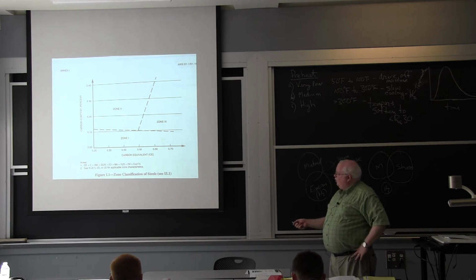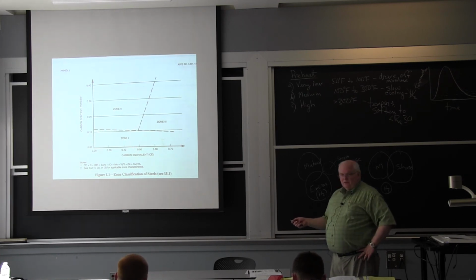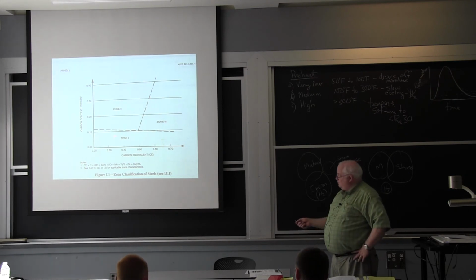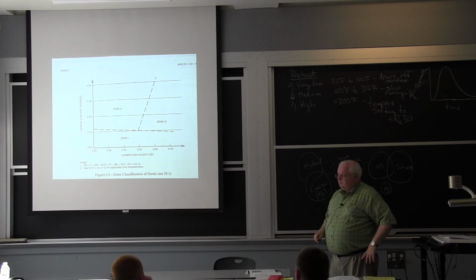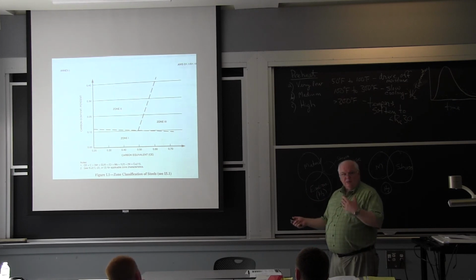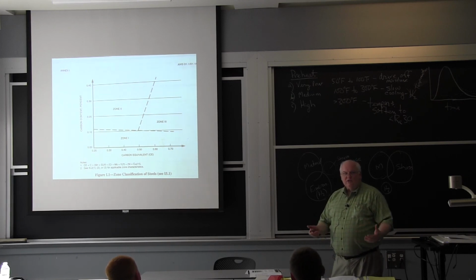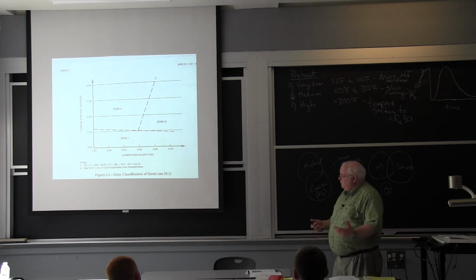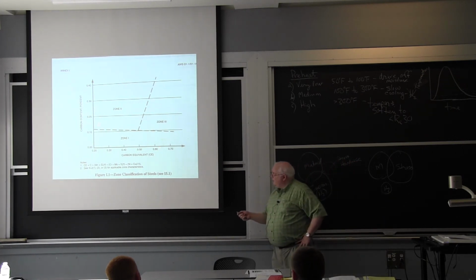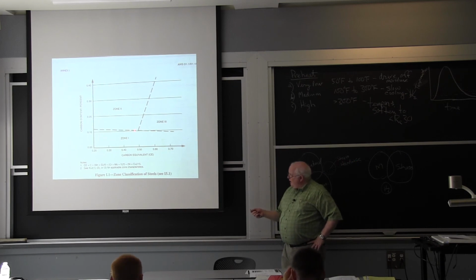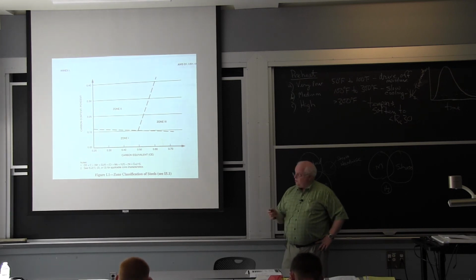And down here in the low hardness zone, less than 10 points of carbon, I can't get high hardness no matter what. So if I want to control hardness, zone 1, those steels are easy to weld. Okay? No matter what their carbon equivalent or depth of hardenability, because 0.1% carbon won't give me more than about Rockwell C30, let's say. Zone 2, I have higher carbon, and so I can get higher hardness, but if my carbon equivalent, the depth of hardening, is not above about 0.5, I'm in pretty good shape.